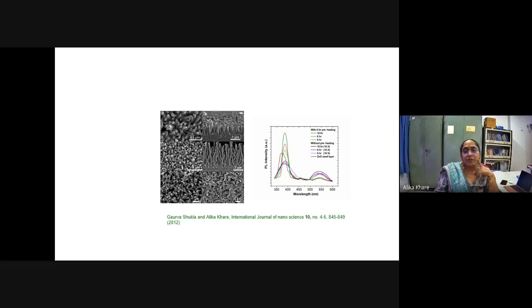So in this way, if we do not have the direct excitation source, we can use multiphoton absorption induced emission. This was also analyzed, though I'm not displaying the result. We could see that here also we were able to get laser action and the longitudinal mode similar to what we got with the 355 nanometer.